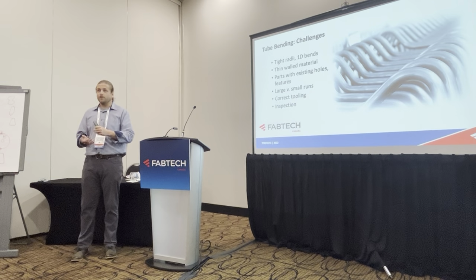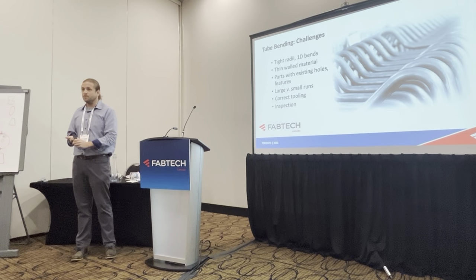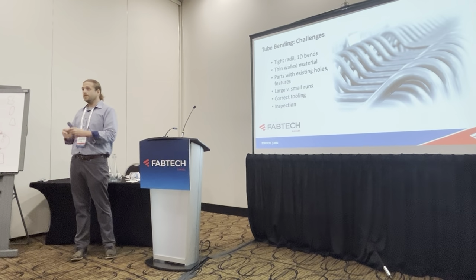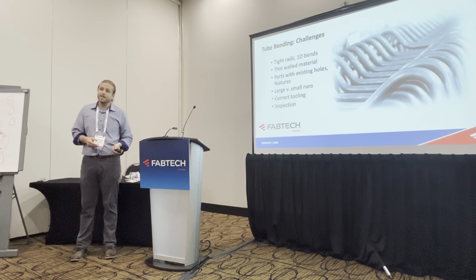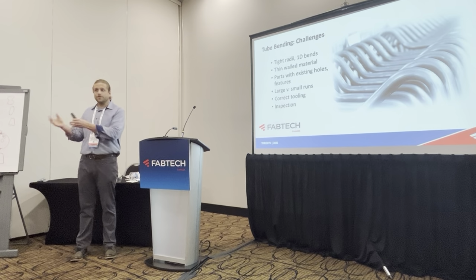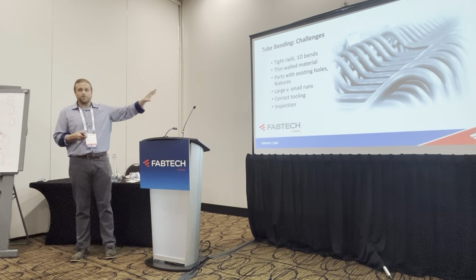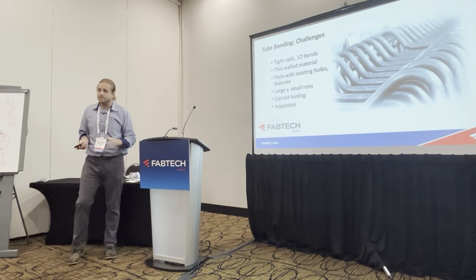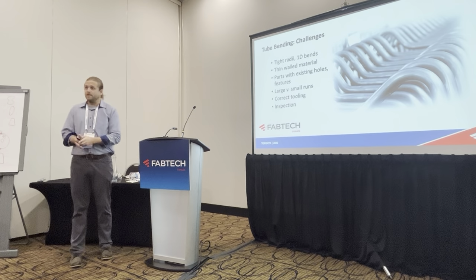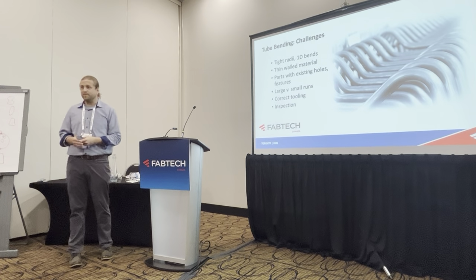You're going to wear out your mandrels, you're going to wear out your wipers, and you don't want to be caught paying for that up front and not charging your customer for that, because there's no way around eliminating those consumables at that level, because as the mandrel wears out, you have to replace it because it will no longer work.